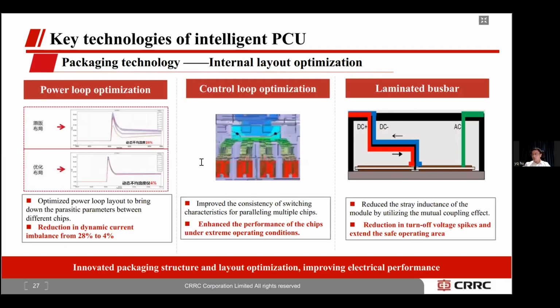Internal layout optimization was also conducted. We optimized the power loop layout to bring down the parasitic parameters between different chips, which could reduce the dynamic current imbalance from 28% to 4%. We optimized the control loop by improving the consistency of switching characteristics for paralleling multiple chips, which enhanced the performance of the chip under extreme operating conditions. We reduced the stray inductance of the module by utilizing the mutual coupling effect, which leads to a reduction of the turn-off voltage spikes and extends the safe operating area.